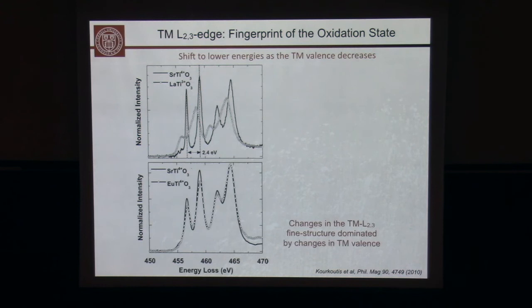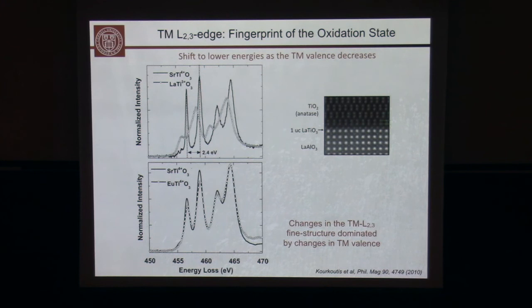Just a quick reality check. Here is a comparison of strontium titanate with europium titanate, and the spectra look almost identical. And this work has been done for many years now. Here's one example of this. So EELS can be used to track changes in bonding. In this particular case, it's a variation in valence states of the material. And so now you can imagine, if you combine an atomic resolution probe with spectroscopy, you can position your probe at the top, record a spectrum at that point, and scan across the interface and measure how the electronic states vary as you go through a well-defined interface.